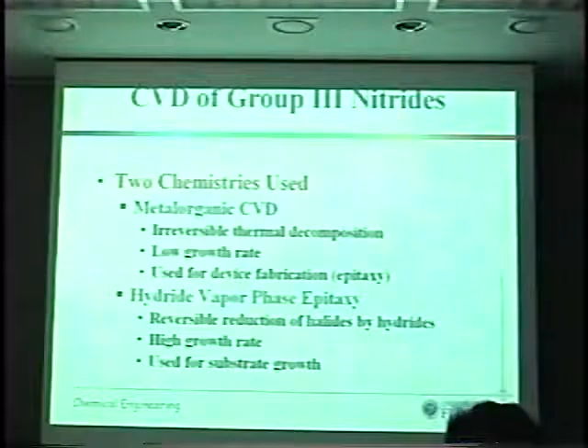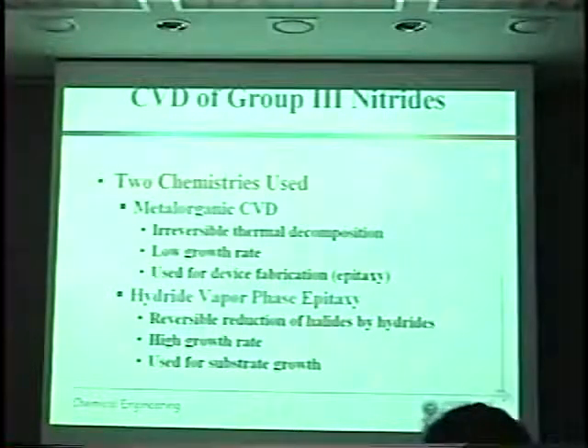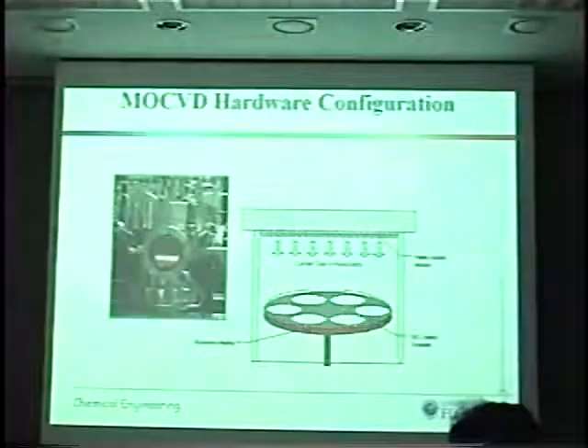Hydride VPE is a reversible chemistry. It's a reversible reduction of halides, and is actually the first chemistry that was developed. And as I said, it usually gives a much higher growth rate, maybe about 100 times higher than you can get from MOCVD. So here's a system.